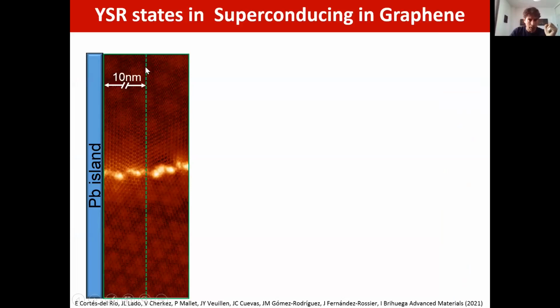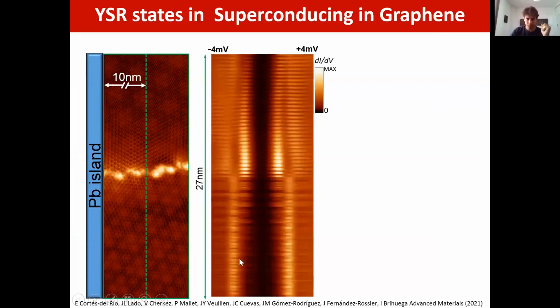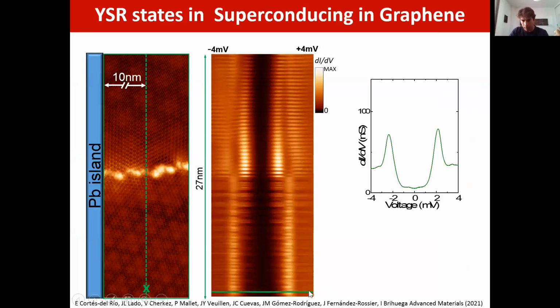And now we are going to analyze the density of states of graphene along this green line, which is perpendicular to the lead island. So it is at a constant distance of 10 nanometers to the lead island. If we do the density of states, this is what we observe. If we want to get the density of states of this point, far away from the defect, we just need to make a cut here. If we make a cut on this plot, then we recover the superconducting properties of graphene due to the lead island. And now you want to know what the density of states is on the grain boundary. We just need to make a perpendicular cut here.